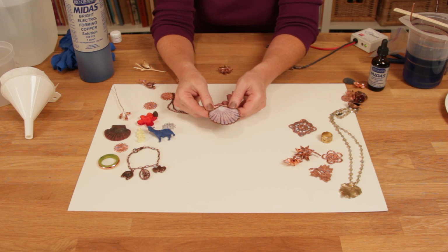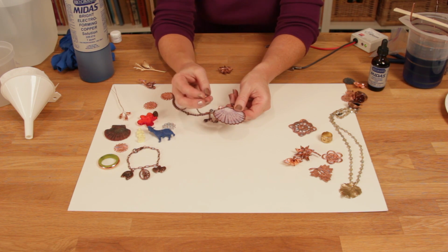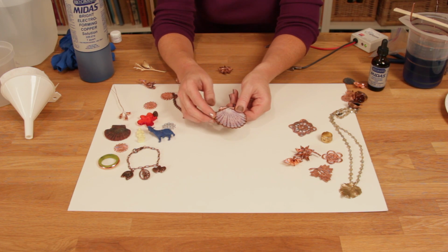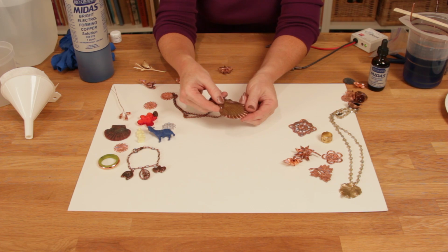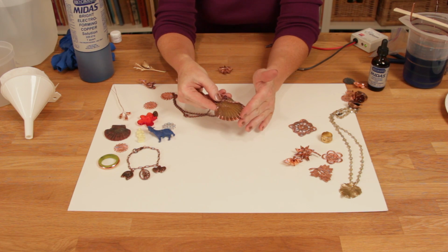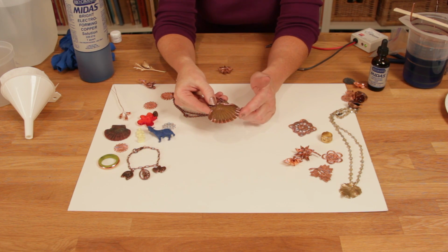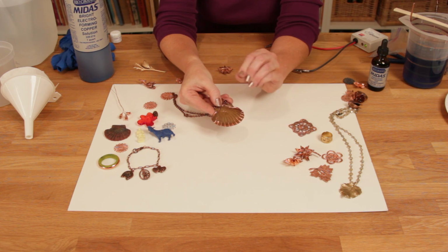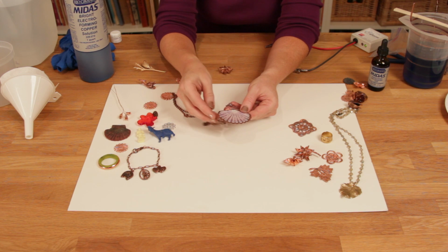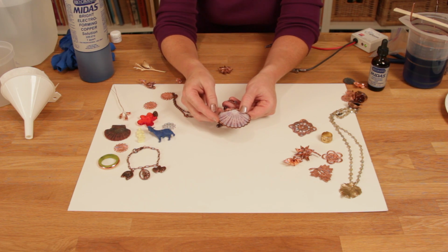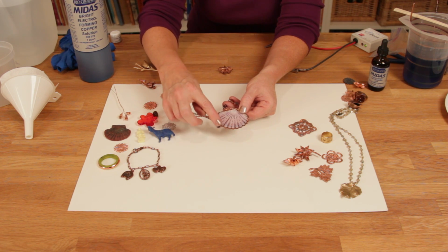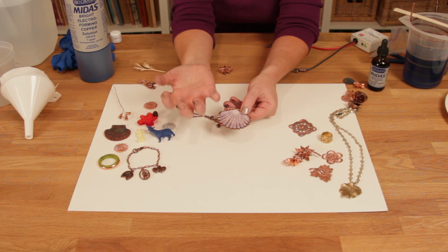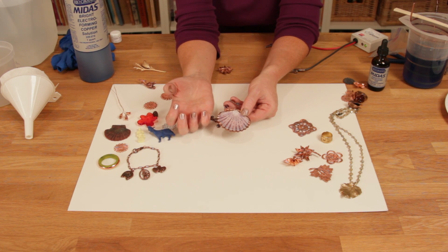Here are a few hints I want to share with you about electroforming. Remember that the plating is not actually embedded or sticking to the piece, but rather wrapped around. So on this seashell, for example, the entire backside is plated with copper, but if I were to stop along the edge and only place the graphite up to the edge, it would peel off. So when I've prepared this piece prior to electroforming, I paint graphite up and over the edge around here so that it hangs onto the piece.